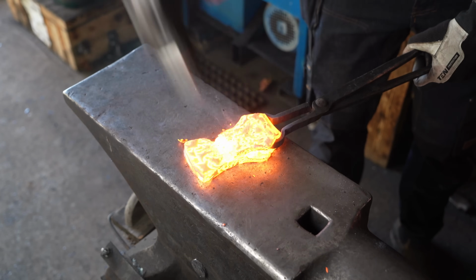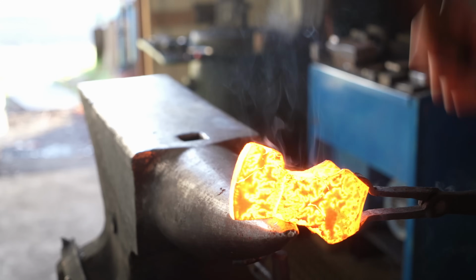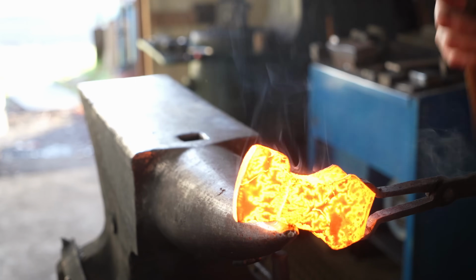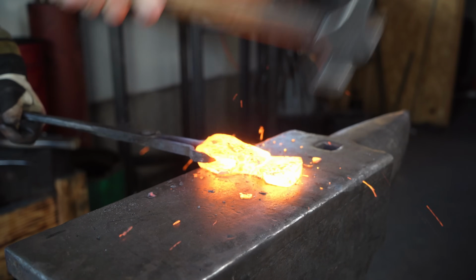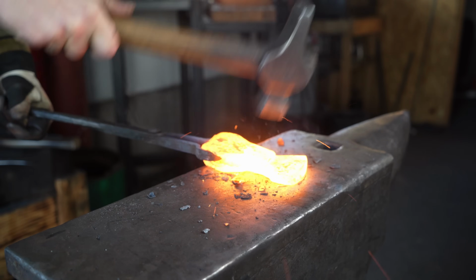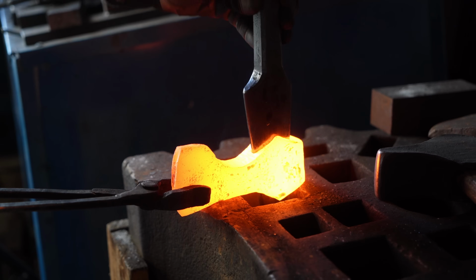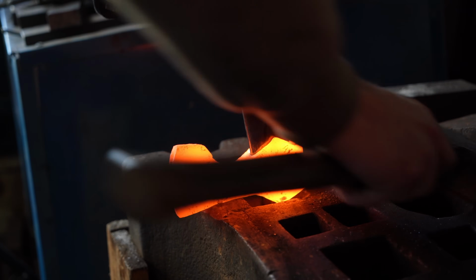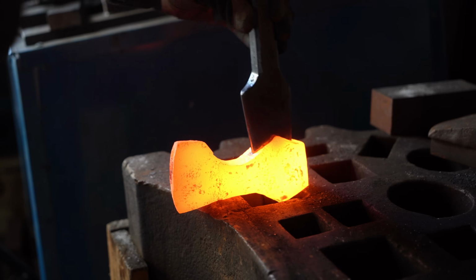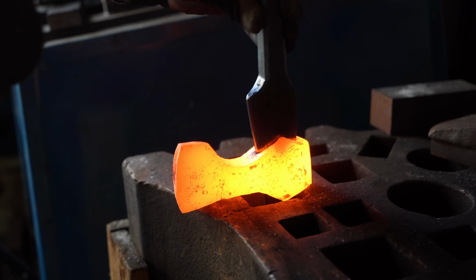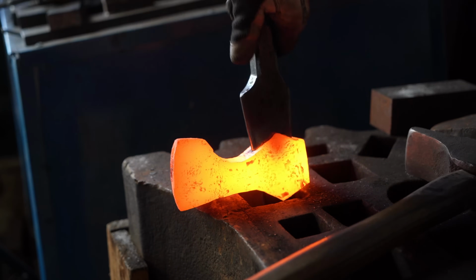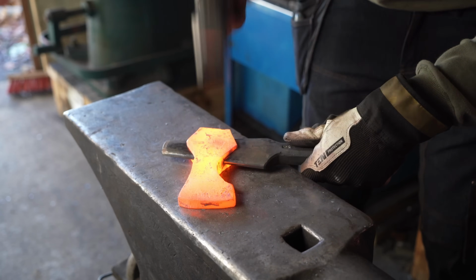I also make sure to blend the welds on the profile of the axe. I find that the pin section of the hammer does a really good job at that. A good way to see if your weld is strong is to carefully drift the eye of the axe. If your weld is weak, the extreme pressure of the drifting will split the eye open. But if it's strong, it will stay shut.